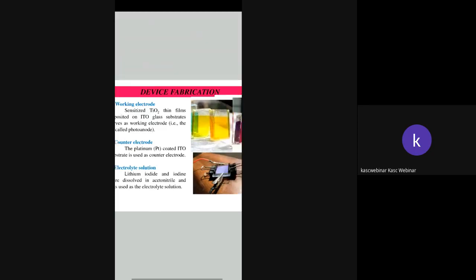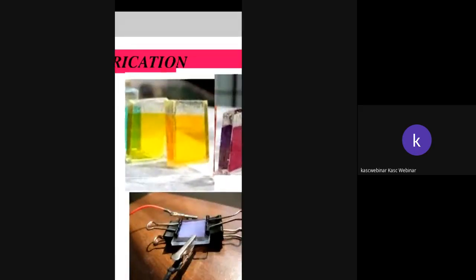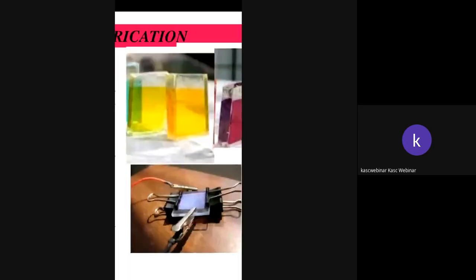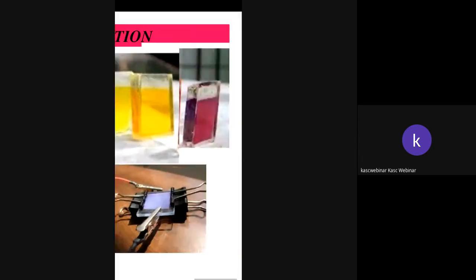Here you can see the sensitized films. The first one, the yellow color coated, is quantum dot sensitized, that is cadmium sulfide quantum dot sensitized TiO2 on ITO substrate. The glass-like structure is the ITO substrate, and over that the yellow color shows the sensitization of quantum dot over the TiO2. And in the next figure, the purple color shows natural dye.